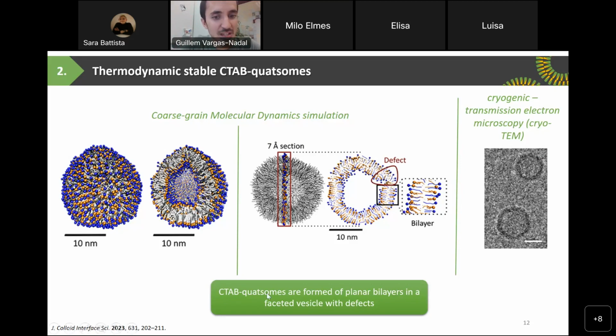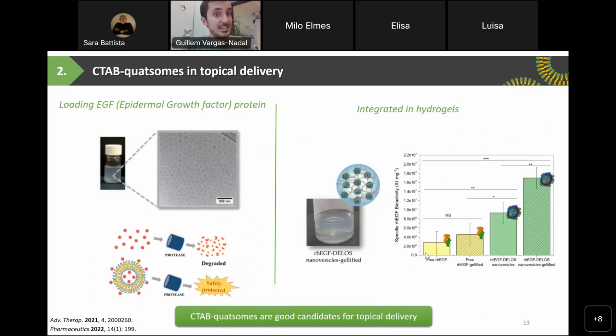So in this case, the quatsomes, the CTAB quatsomes, are formed of planar bilayers in a faceted vesicle with defects, and these defects give the quatsomes the property to be thermodynamically stable. This is important: it is not the asymmetry, it is the defect that gives this property. Also, the CTAB quatsomes have been used in topical delivery.